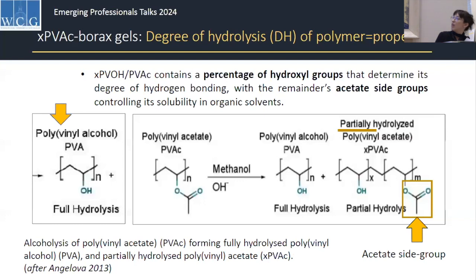Next slide, please. This is just a brief little detour in the chemistry of it, just to explain that the hydrolysis of the polymer is actually very crucial to the success of gels, depending on what you're trying to put in them. And this is a diagram from Angelova, who's done a lot of work. All her early career has been on the polyvinyl alcohol borax gels. And really what we're after are polymers that are partially hydrolyzed, the low hydrolyzed polymers. They've got more acetate side groups, which means that they can facilitate solubilization in organic solvents and greater proportions of those.